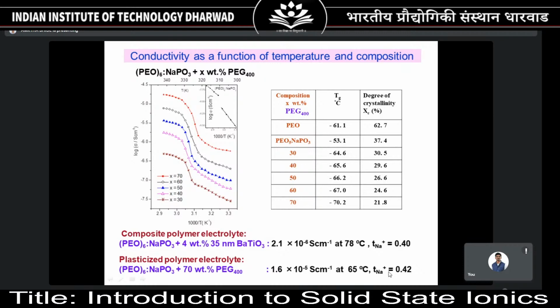at 65 degrees Celsius. So upon adding barium titanate, you could get an ionic conductivity of the order of 10 to the power minus 6 Siemens per centimeter at 78 degrees Celsius, which, if you remember the previous one at around 78 degrees Celsius, was 10 to the power minus 8. So you got an enhancement of 2 orders of magnitude. And when you go for plasticized polymer electrolyte, we could get roughly 3 orders of enhancement in the conductivity.